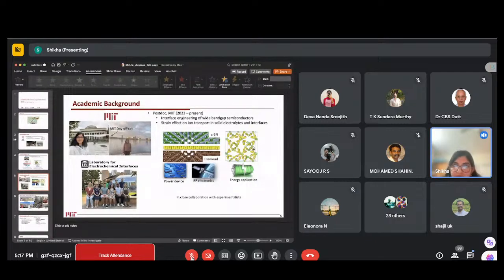Yes. So that is the idea here. One thing is always creating, as I mentioned, creating the defects in our favor. When we do the synthesis, we always have defects, or when we add something, we say okay, we are creating defects or we are allowing them. In this case also, because we want the transistor out of these interfaces, I want higher conductivity, higher mobility. So I do not want defects which will harm my system. And when we modify the system, we are creating defects even in electrolyte battery materials. We are creating defects to get more conductivity, more ion transport.